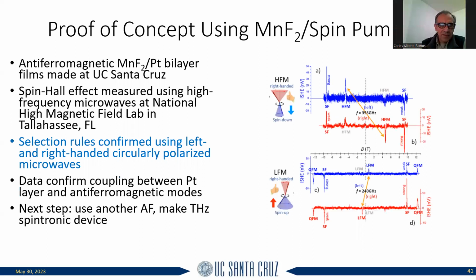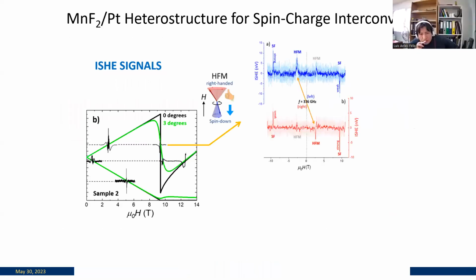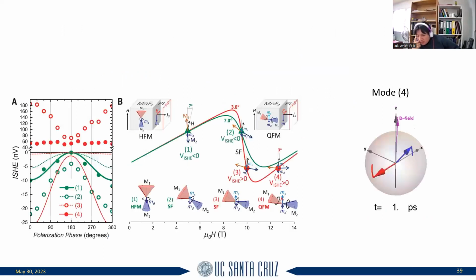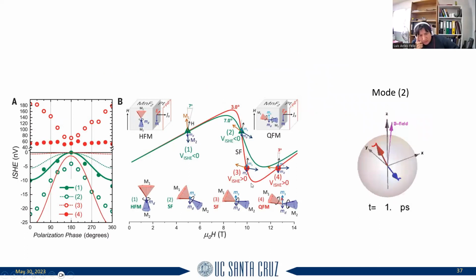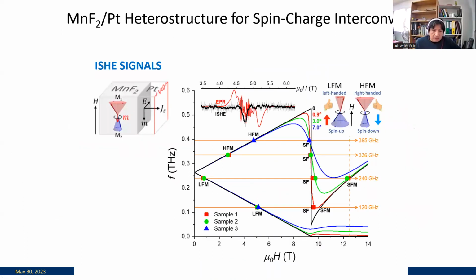And I have an additional question. Why does your inverse spin Hall effect signal not follow your EPR signal? I was expecting a similar shape to your signal, because if you take a closer look at your EPR signal, one could say that the resonance is around 4.5 Tesla and 5.2 Tesla, according to the EPR, but in the inverse spin Hall effect signal it is around 4.7. Is that reasoning correct?